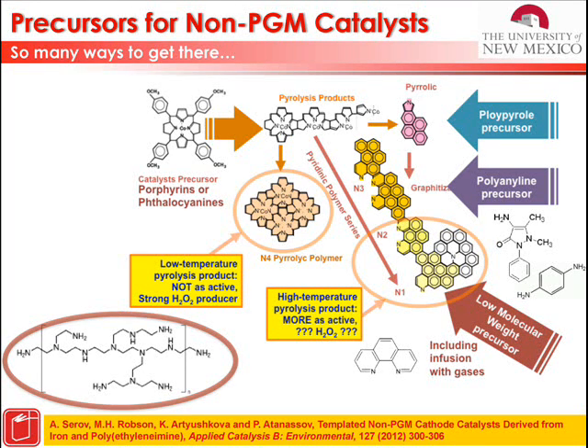You can under-pyrolyze your catalyst, you'll end up with a pyrrolic-like pyropolymer that will produce a lot of peroxide and never will reduce oxygen to water. You can lock that structure in further with a fast quenching and have a graphitic material with a lot of pyrrolic nitrogen. Or you can further pyrolyze with a longer pyrolysis and obtain different populations of defects.